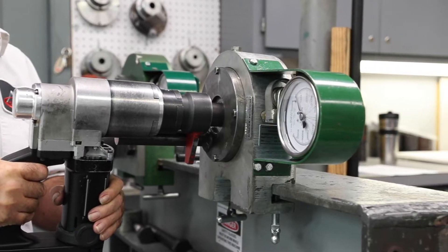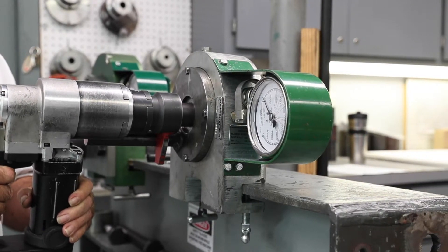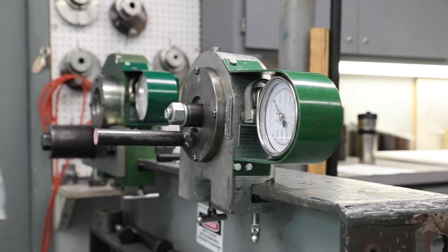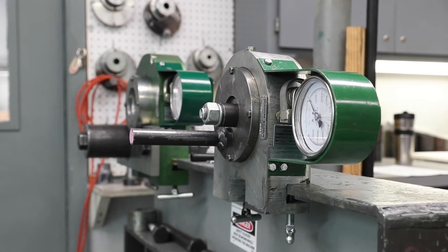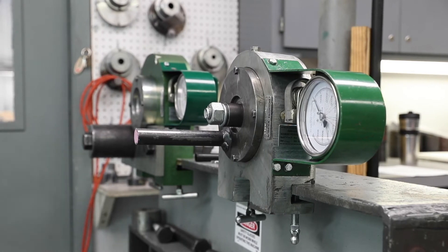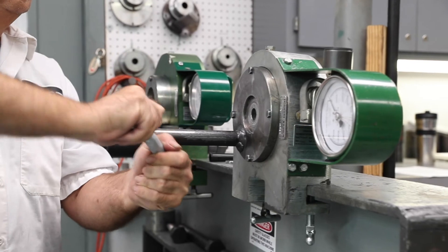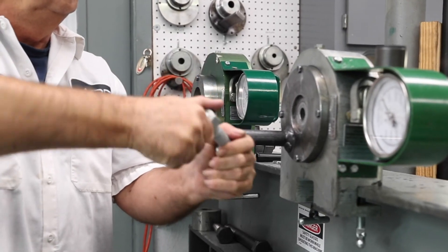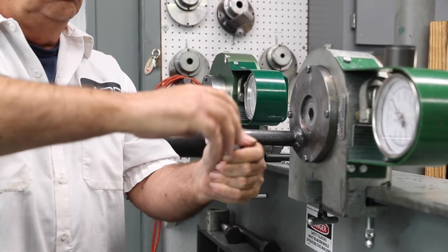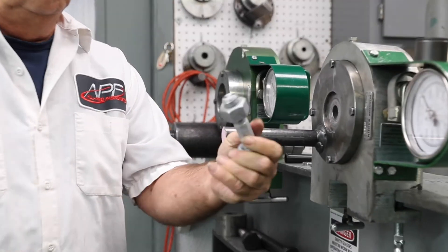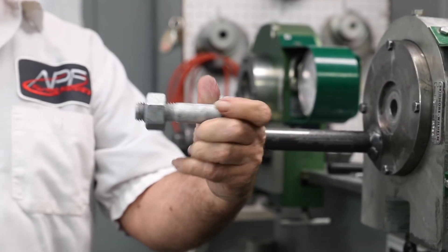The nut and bolt assembly is then removed from the torque tension tester. Assemblies that strip or fracture prior to this rotation failed the test.